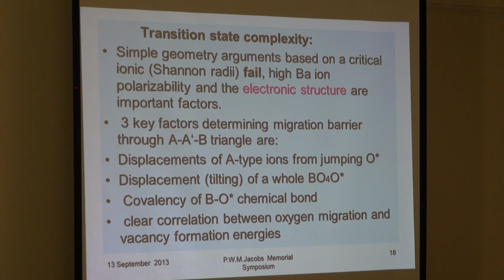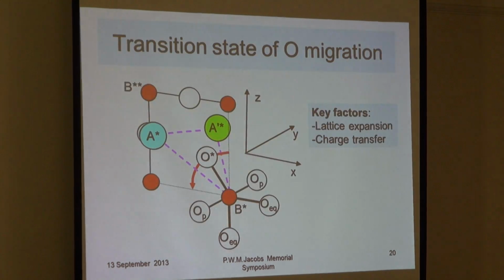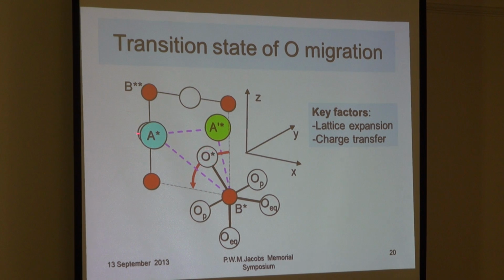But also, what we found is there are three key factors determining the migration barrier. So first is, as shown here, that in the saddle point, or transition state, oxygen goes through a triangle of two A-type cations and a B-type cation. And the first factor is just deformation of this cage. And when there is more space, it's easier to migrate and the energy will be smaller. This is the first important factor.